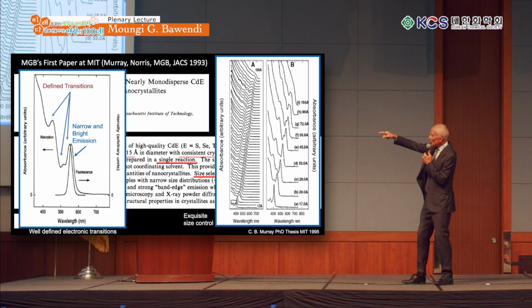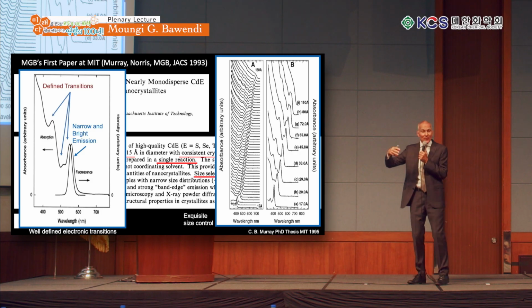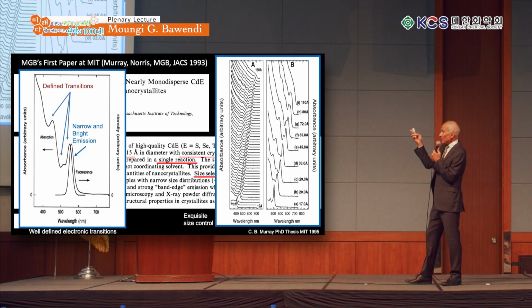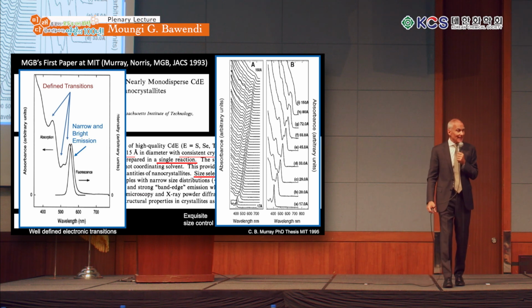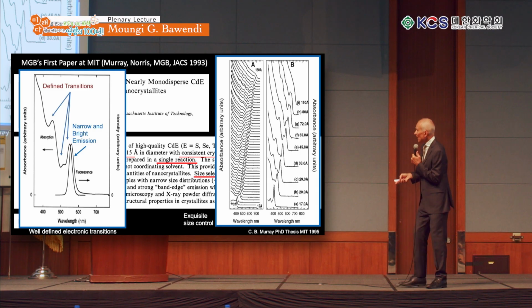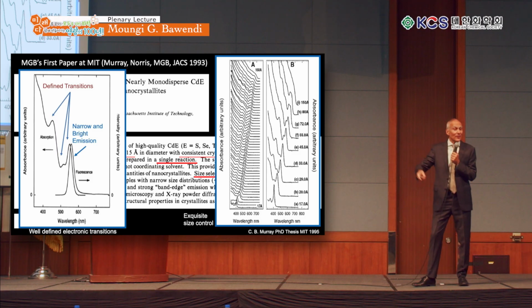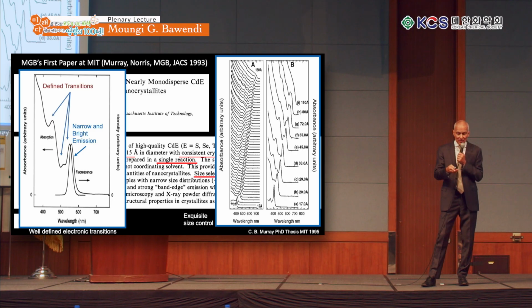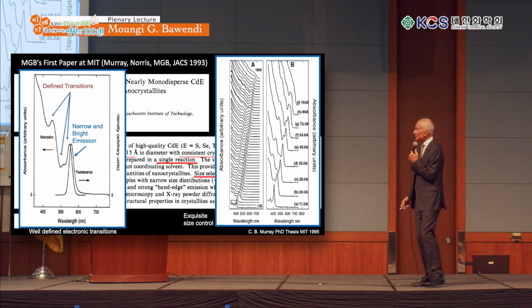And we see the trajectory as the particle size, or the cavity, gets bigger and bigger, the particles get redder and redder. And the difference in the number of atoms between any two of these spectra is not very many. It's a handful of atoms. And so just by picking the time to take the samples out, we could really control the size with exquisite control. And that allowed us then to study the relationship between the fundamental and the harmonics in the waves that the electron had in the cavity.